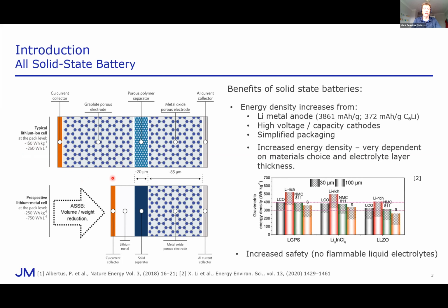And this simple schematic clearly shows the volumetric energy density improvements that can be achieved. According to this data here, you've got 250 going up to 750 watt-hours per litre. Now, the gravimetric alternative has a few more subtleties at play. It comes a lot down to the choice of materials and the way you process and deposit those materials. But I should point out that both of these are highly dependent on the successful inclusion of the lithium metal anode into the system, primarily because of its near tenfold increase in theoretical capacity compared to lithiated graphite.